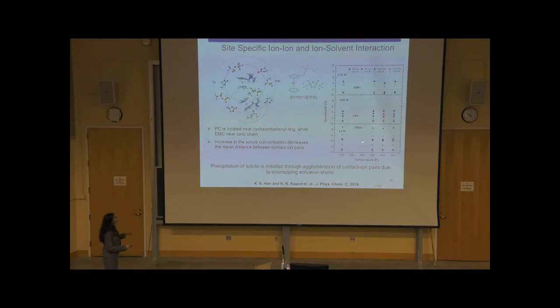So what happens at this higher concentration is that different solvation shells start overlapping, and these cations start sharing the anions. So the precipitation of solute is initiated through agglomeration of these different contact ion pairs due to overlapping of solvation shells. So if you want to design a solvent mixture to increase the solubility of this ferrocene salt, we need to ensure that we use a solvent molecule or a complicated mixture of solvent molecules that maintain this relatively strong ion and solvent interaction and do not let these contact ion pair shells overlap.